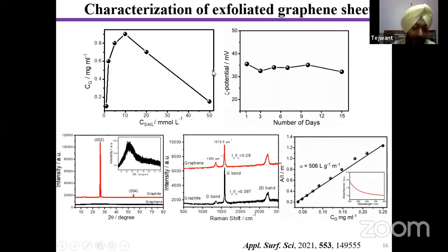The exfoliated graphene has been characterized by XRD spectra. Here one can see in the first of the figures, okay, I'll annotate it, in the case of graphite, it shows very crystalline nature and a very high scattering intensity for the peaks corresponding to the 002 plane and 004 plane. However, when you have exfoliated the graphene, single layer or few layer graphene, its stacking is reduced. One can see that there is no high intensity peak in the case of graphene. That shows the graphene has been exfoliated by the appropriate method.